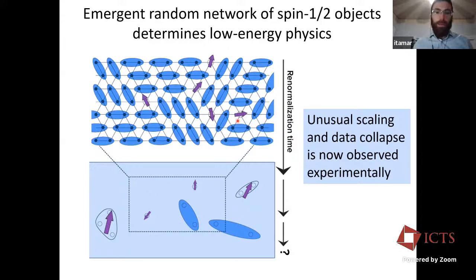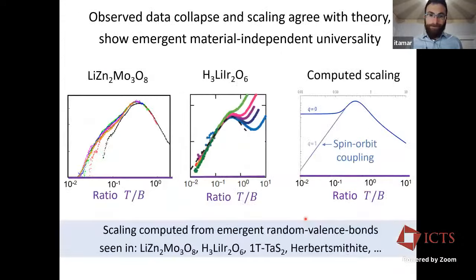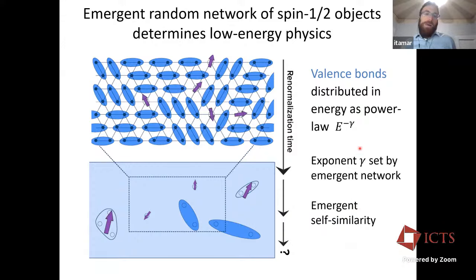Okay, let me also say one other thing. The exponent is allowed to flow. So calling it a single exponent is only an approximate description. Really, as a function of RG time, that exponent could, in principle, flow. So it may not be a single exponent, which is not extremely satisfying, but that may be the physical answer. I see, but doing the fit is tricky, and we can talk more offline. Sure, I'll write to you. In other words, this e to the minus gamma exponent, the gamma itself changes with the energy scale, roughly, that's what you have in mind. Yeah, that's right. So this is really an assumption, e to the minus gamma.